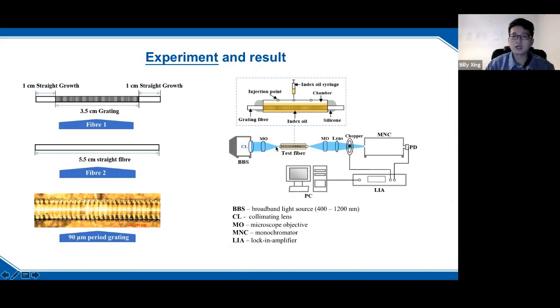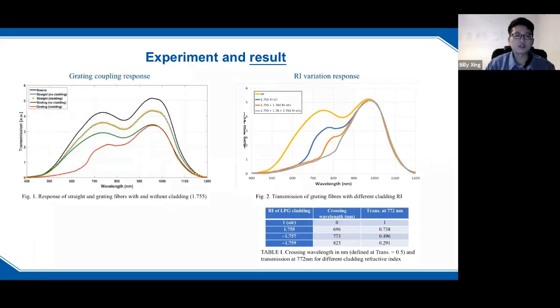So here is our experiment setup. We have broadband light going into the fiber, collected by a monochromator, and we analyze the data on a PC. Here's the coupling response for the straight fiber. For the reference, the black line is the light source spectrum, and the blue line is the straight fiber without cladding. Once we add the cladding, immersion oil, index oil in this case, we can see that for the straight fiber there's no change. But under the same condition for the grating fiber, we can see it drops in the region of 600 to 800. That indicates that the long period grating actually works. It is a coupling effect between the incident light and the grating, and part of the light is lost into the environment.